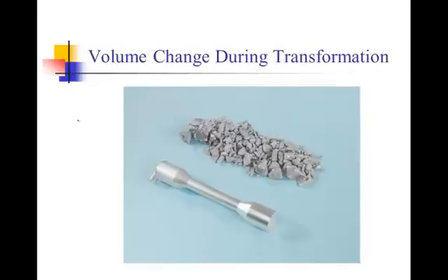And by adding impurities such as yttrium to the material, or sometimes calcium or magnesium or cerium, we can cause some empty atomic sites in the structure, some vacancies, which can accommodate that desire for the material to expand and to keep that from happening so the material doesn't fall apart.